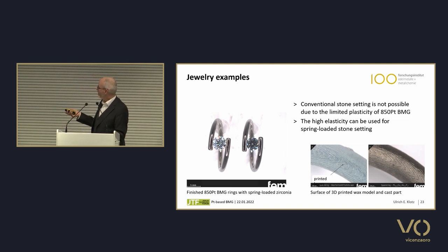If you look at the surface of the ring, you see the 3D printed and the cast surface, and you get a perfect representation of the surface. So the form filling ability is really very good.